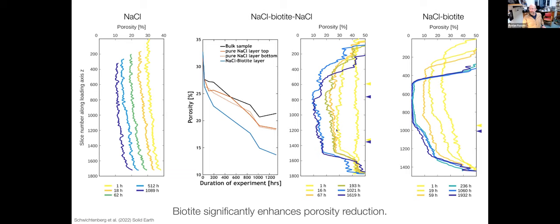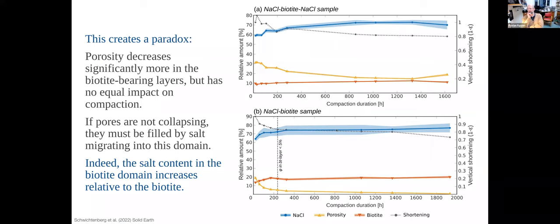Now, some of you may already have realized that this created a paradox, right? What we do see is that the sample doesn't compact preferentially in these biotite bearing layers, but the porosity decreases preferentially there. And what we thought would decrease the porosity was mechanical compaction. And that didn't happen, right? It absolutely didn't happen. So if the pores are not collapsing, they must be filled. That's the other way you can reduce porosity. And that's what happens. The salt content increases in these layers. The salt content here is shown in blue. These are for two samples.